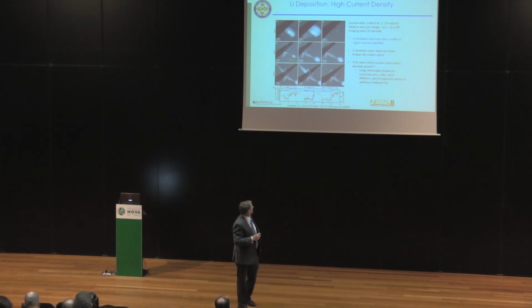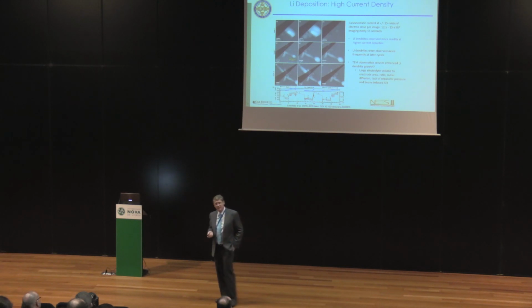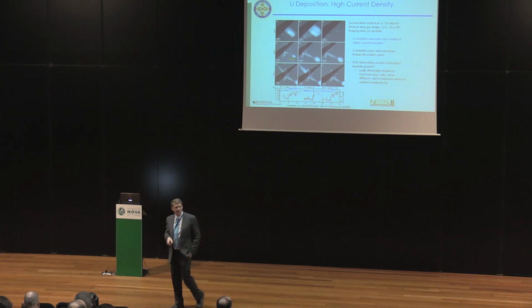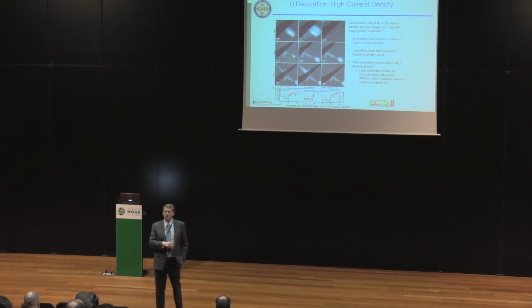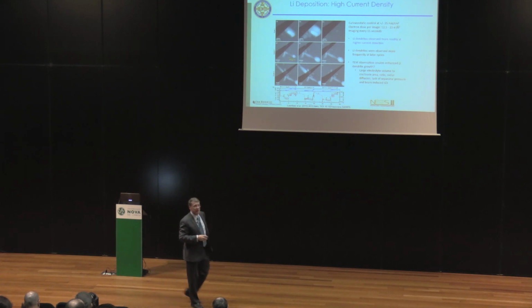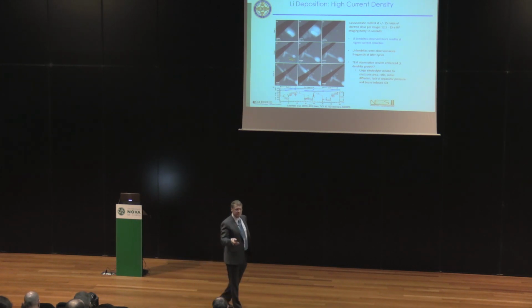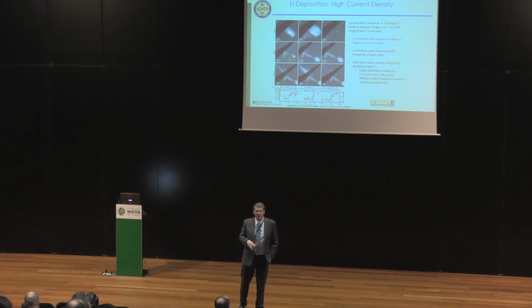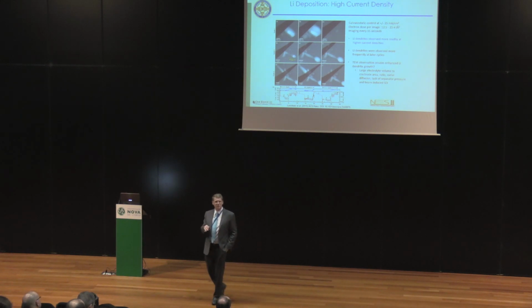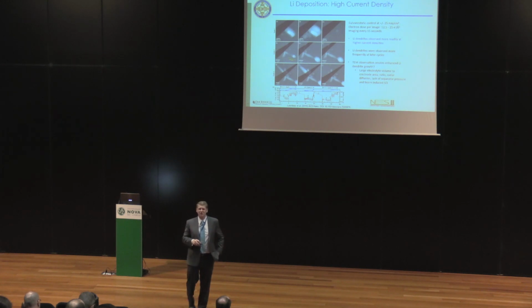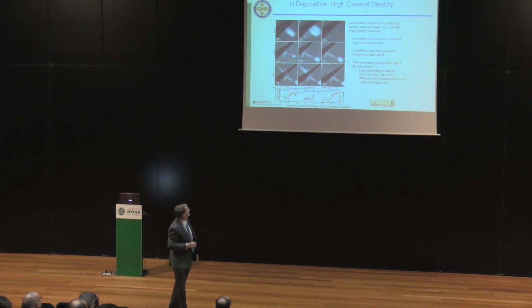Well, they also increased the current density. Right, so what's one of the other obvious knobs that they have? So the previous depositions were all done at this 10 milliamps per square centimeter. In this case, they increased the current now to 25 milliamps per square centimeter. So fairly high. I would think that 50 is what I would call a very fast plate of lithium. 25 is reasonably fast. 10 is fairly normal. And if you see a presentation where someone's talking about 1 milliamp per square centimeter, that's a pretty low rate of charge.